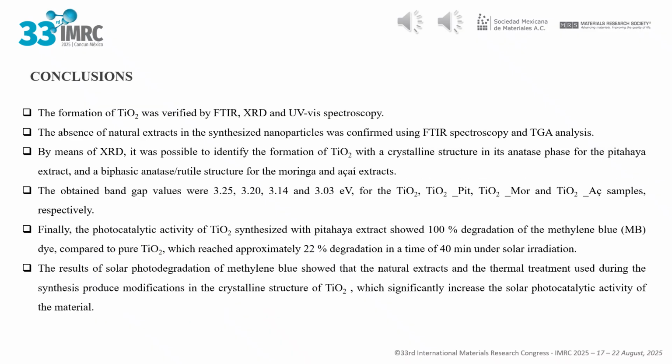Conclusions. The formation of TiO2 was verified by FTIR, XRD and UV-vis spectroscopy. The absence of natural extracts in the synthesized nanoparticles was confirmed using FTIR spectroscopy and TGA analysis. By means of XRD, it was possible to identify the formation of TiO2 with a crystalline structure in its anatase phase for the pitahaya extract, and a biphasic anatase/rutile structure for the moringa and acai extracts.